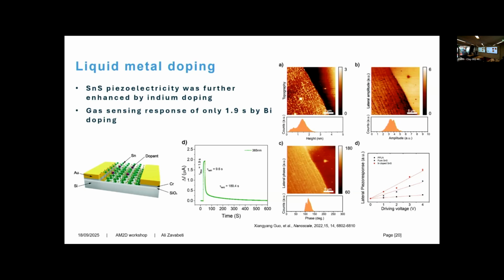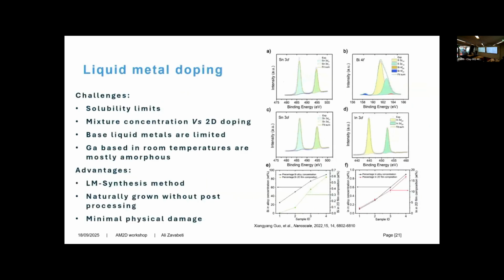I'm showing this because I would like to mention that this type of doping is generally not done in situ. Either it is done as a post-treatment by irradiation, but this is an in situ growth. We mix them as an alloy, and then we print them as a single layer, so they are not post-treatment. They are in situ growth using liquid metal methods. As I mentioned during the introduction of the liquid metal chemistry, the ratio of added element in the base liquid is different from what ends up in the 2D film because of the differences in Gibbs free energy of formation or the combustion energy. So we sometimes add a very high ratio of less reactive material to get just a little bit of doping in the oxide layer.